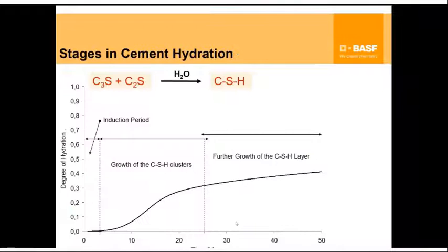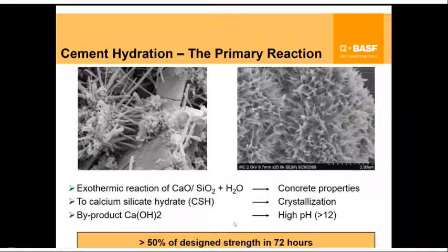One of the orphans in the chemistry of concrete is calcium hydroxide. It actually has a lot more benefits than one really gives it credit for. It keeps the pH really high. It helps reduce the propensity for corrosion in concrete by passivating the iron rebars. But it also ensures that the CSH formation is happening on a regular basis in order to generate the calcium silicate hydrate, which then becomes the key property of concrete. And typically you get greater than 50% of the design strength in 72 hours.